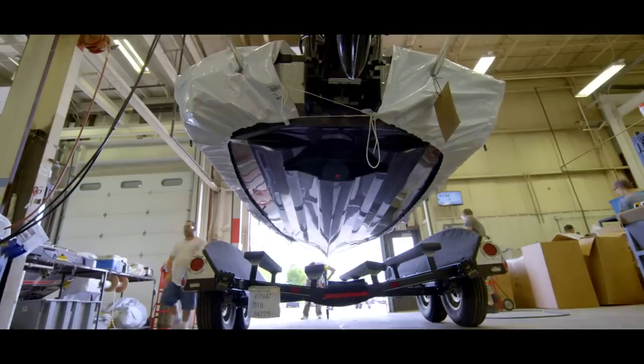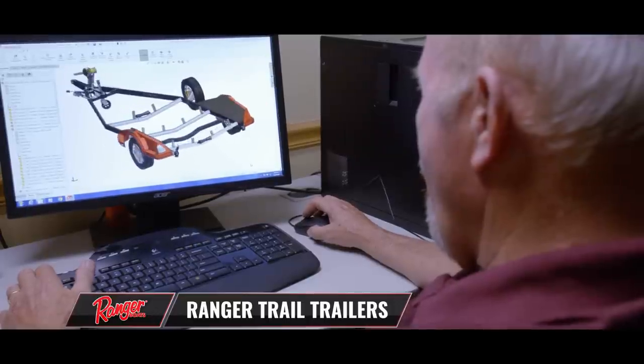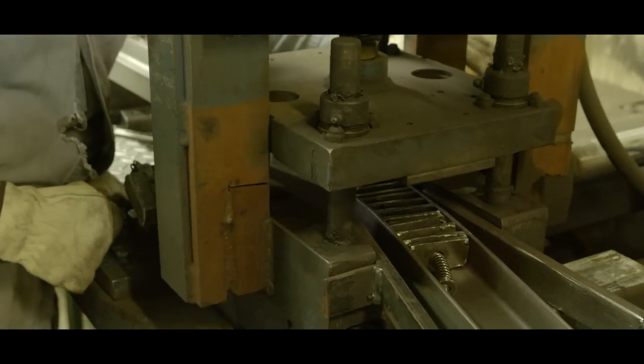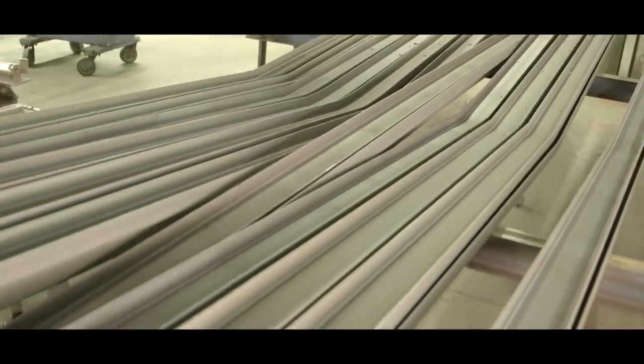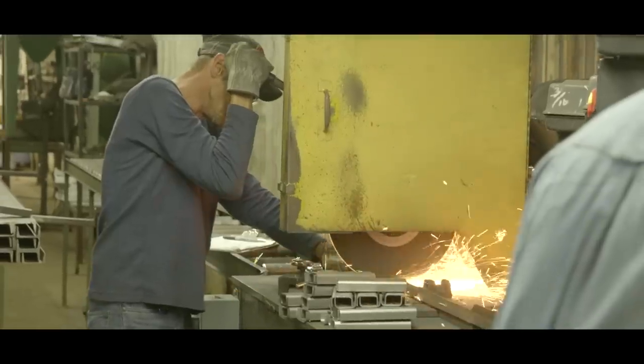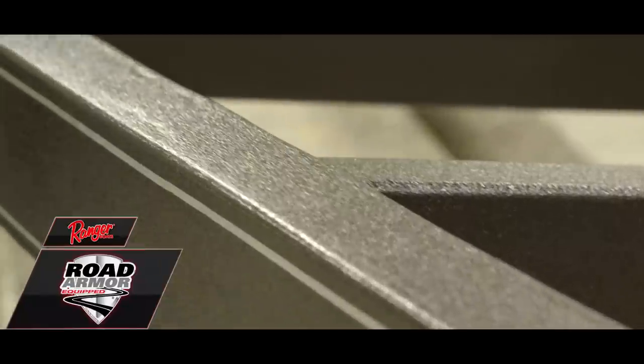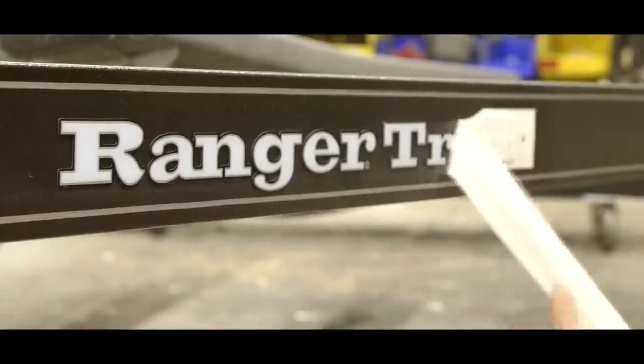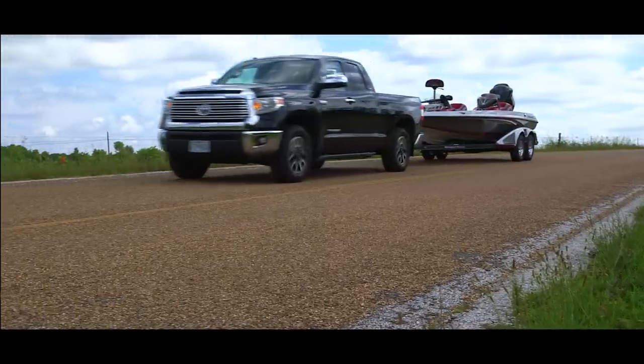Finally, your new Ranger meets its custom-built Ranger Trail trailer. Ranger pioneered custom-fit trailer designs, and today Ranger Trail sets the standard in quality, safety, and longevity. Every curve and every weld is formed in a closely monitored environment to ensure the highest quality from beginning to end of the production process. Every trailer is built from channel steel instead of tube steel, because tube steel has a closed-off interior that traps moisture and can rust from the inside out. We also add a special blend of Road Armor-equipped coating to our frames — a super-tough polyurea sprayed-on coating similar to popular truck bed coatings.